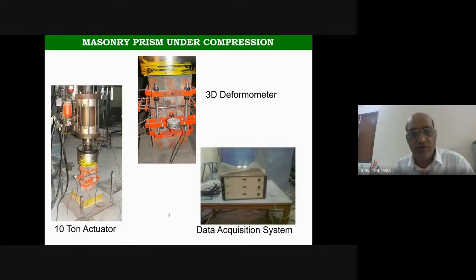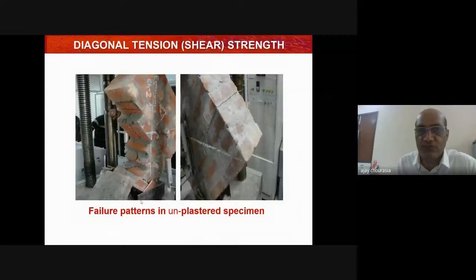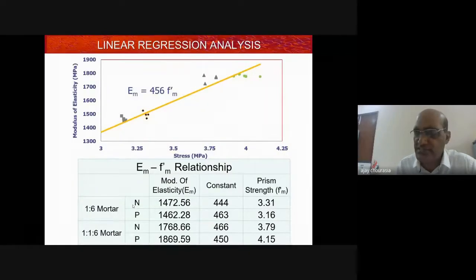In India, the compressive strength or crushing strength of the burnt clay brick unit ranges from 3.5 MPa to 18 MPa. In Calcutta and the northeastern region, you will see high compressive strength, whereas in the southern portion, below Maharashtra, the compressive strength of the bricks is very poor, even less than 5 MPa, sometimes even less than 3.5 MPa as well. The minimum prerequisite for compressive strength is 3.5 MPa. So we have understood all the engineering properties through detailed experimental investigation of units, mortar, and masonry wall panels. An important thing is, we have also conducted the diagonal shear test as per ASTM E519 to understand the shear strength of masonry walls and its failure mechanism as per the protocol given in ASTM E519.